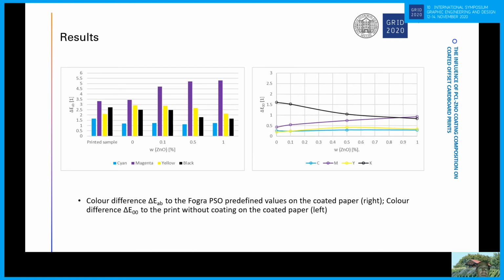On the coated papers, there is some different behavior. So on the right side, we can see that the delta E 2000 values are even lower than on the uncoated paper, but we can see two trends. One is the decreasing values of the color difference in black and the increasing values of color difference in magenta. And this increasing color difference in magenta, although it's really low, the highest is 1 at